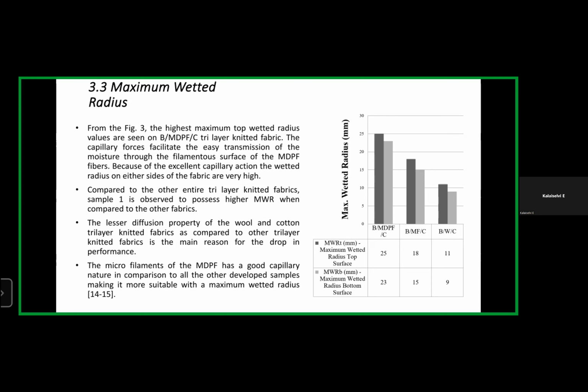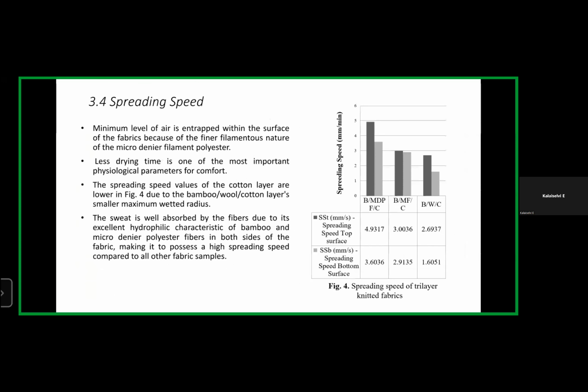The lesser diffusion property of the wool and cotton tri-layer knitted fabric as compared to the other tri-layer knitted fabrics is the main reason for the drop in performance. That means the lesser diffusion properties of the wool. The filaments of the microdenier polyester filament have good capillary nature in comparison to the other developed samples. Only because of that, the maximum wetting radius is found.